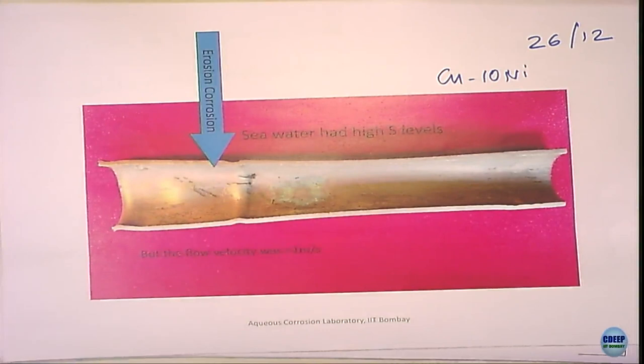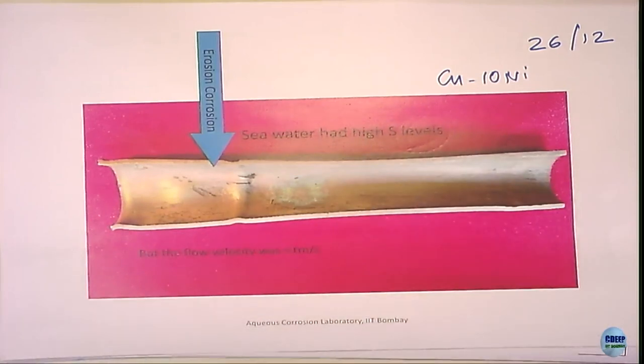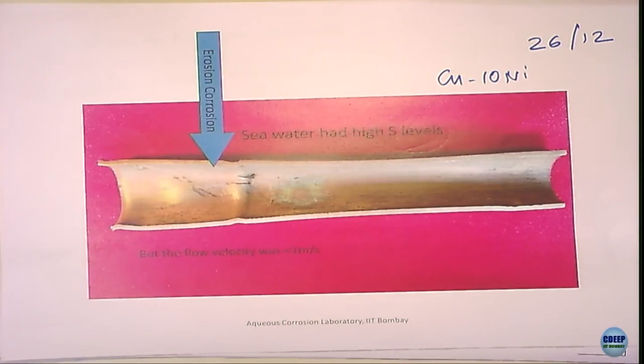The third problem that adds complexity is, if you look at the seawater, the sulfur content in the seawater is quite large. Copper is not stable in sulfur, and neither is silver, but nickel is stable in sulfur-containing environments. Where does sulfur come from? It comes as sulfides. Where do sulfides come from? The sulfides come from degradation of all this, you send it to the sea, right, so many organic matters and biofouling. All this will happen. So the indirect effect is that water purity is very important when you have sulfur. Then there is an issue here.